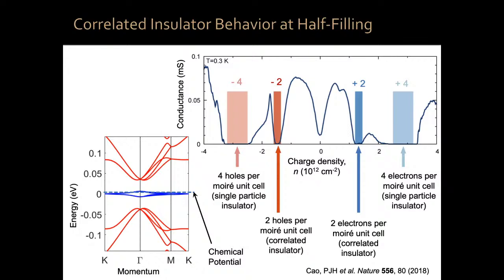The same thing happens if I put 2 electrons per Moire unit cell. The conductance also becomes 0, okay? And that is, again, despite the fact that in single particle physics, simple quantum mechanics should tell us this is a good metal. It's not. It's an insulator. Okay? This behavior only happens when the twist angle between the 2 graphene sheets is in a narrow angular range around 1.1 degrees. Okay? If you put 0.8 degrees or 1.3 degrees, none of this happens. The system is a very good metal at 2 electrons or 2 holes per Moire unit cell. Now, that was the first thing that we discovered.